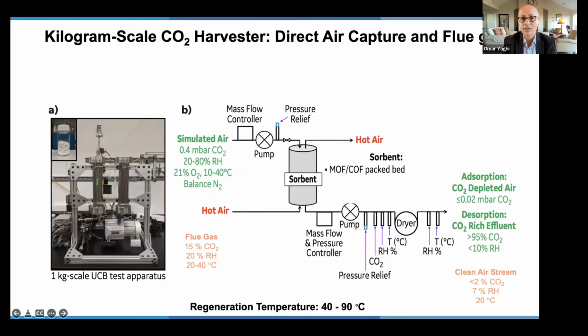Okay, so we took this system and scaled it up to a kilogram to make this CO2 harvester. And you can see here that the sorbent is placed in two compartments so that one can do the adsorption while the other is doing desorption. And here you see that this is simulated air. This is exactly the amount of CO2 in air right now. And you can see that we can cleanse that air from CO2 and reduce it down to less than 0.02 millibar from 0.4 millibar. That's 400 ppm down to 20 or so ppm.